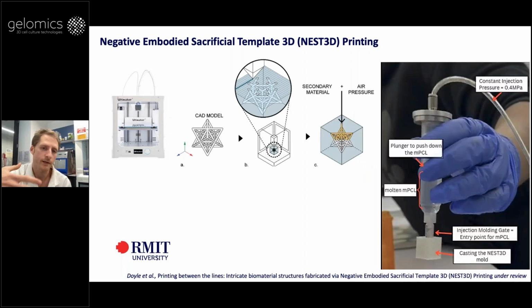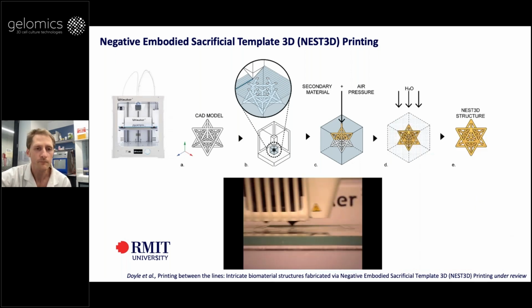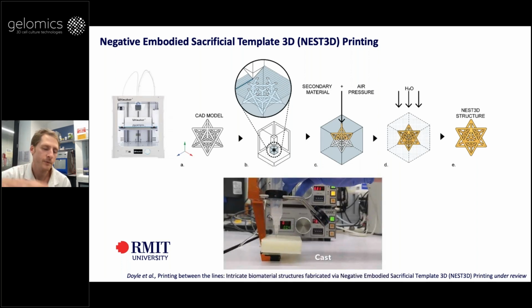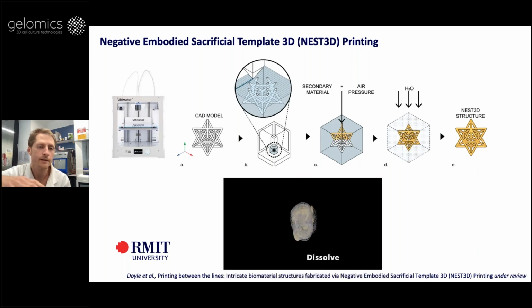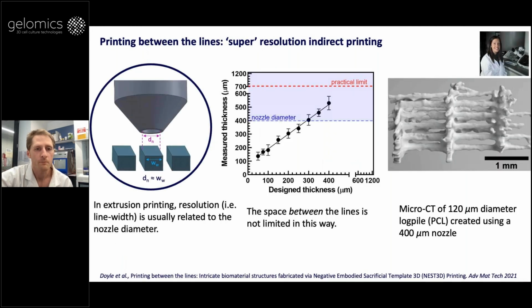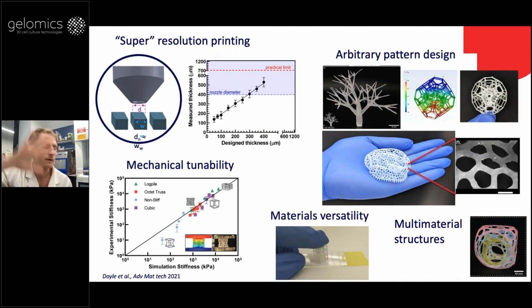Basically, we developed an injection molding process where we screw in a syringe containing our material, and then inject the material. So the first step is to print the mold. Secondly, we cast in what we want, and then we dissolve the mold away. This is polycaprolactone again, creating a human scale ear structure. Because the spaces between the lines can be defined, it can be any kind of distance. You can get higher resolution than defined by the nozzle. You can create complex structures, again using polycaprolactone or acrylic or silicone, and we've even used hydrogels for this process.